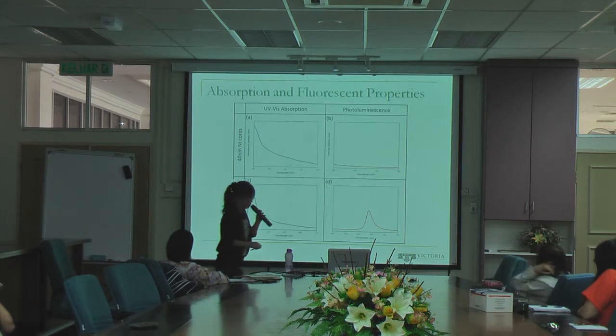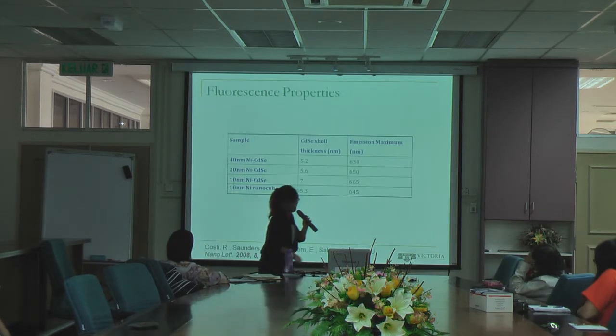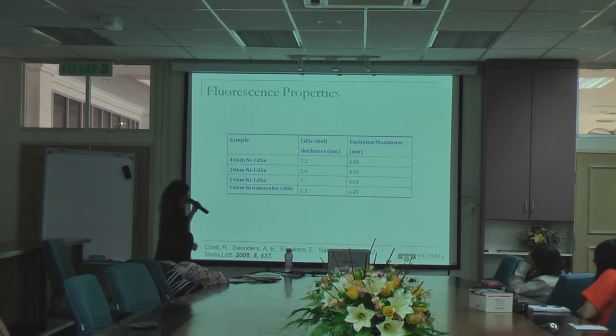Another thing that we notice is that there's a relationship between the particle size of cadmium selenide and the emission maximum of the fluorescence. As the particle size increases, the emission wavelength also shifts to longer wavelength. This is in agreement with the quantum confinement theory.